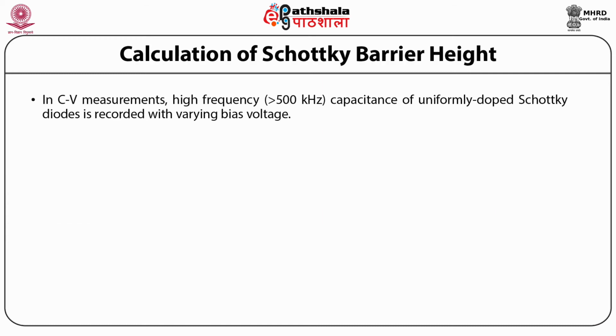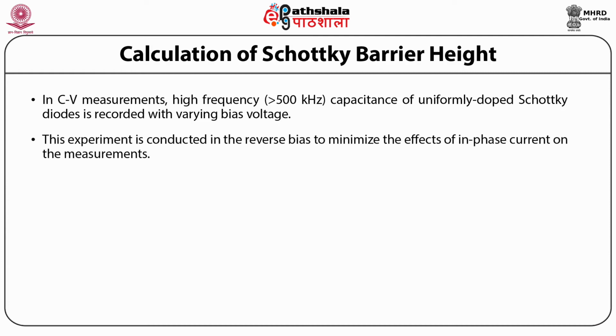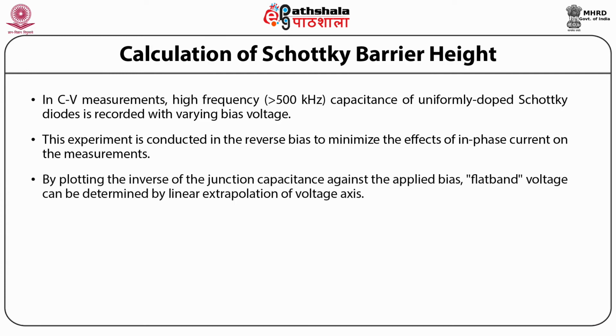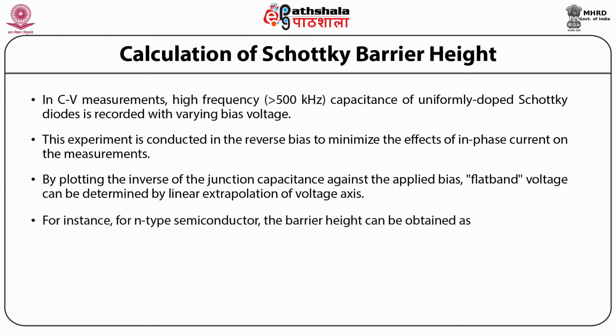In CV measurements, the high frequency, that is greater than 500 kHz, capacitance of a uniformly doped Schottky diode is recorded with varying bias voltage. This experiment is conducted in reverse bias to minimize the effect of in-phase current on the measurements. By plotting the inverse of the junction capacitance against the applied bias, flat band voltage can be determined by linear extrapolation to the voltage axis. For instance, for an N-type semiconductor, the barrier height can be obtained as phi_BN equals V_bi plus V_n plus k_B T. This is represented as equation 5.